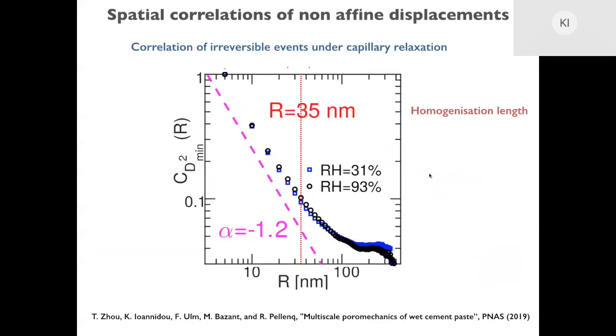Also here we can see the correlation of these events. The correlation of these events has a power law dependence, which has been observed also in glassy systems, but in our case, because cement has these pores, you can see that these events are somehow arrested by the pores. So their correlation length coincides with the length that we have found from scattering experiments, and this is due to the pores. So in a way, the pores of cement are helping to arrest this type of irreversible deformation that might have led to cracking.